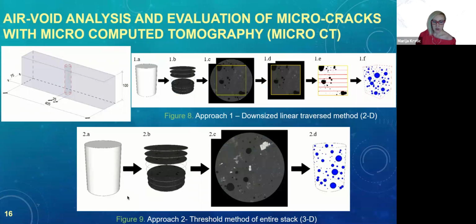However, we also wanted to see what the air void analysis of hardened concrete would be after some time. So in order to do that, we used microcomputed tomography, or micro CT scan. Beams that were exposed to freeze-thaw cycles were used for determining microcracks in the samples, and beams that were not exposed to freeze-thaw cycles were used for taking cores for determining the air void parameters such as air void content, spacing factor, and specific surface of air voids.